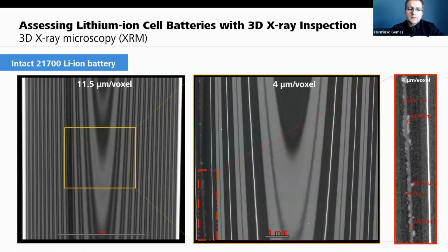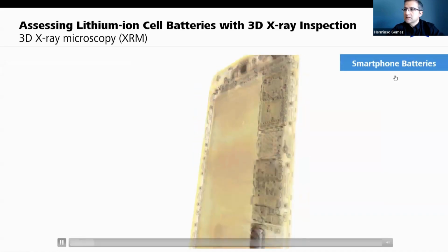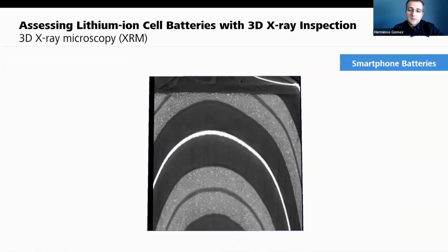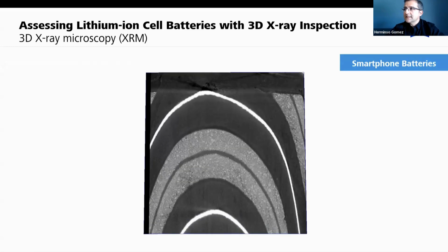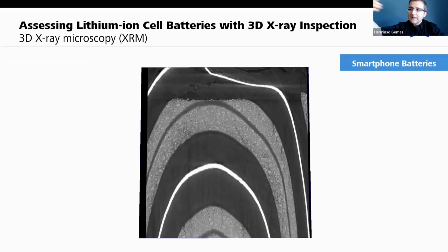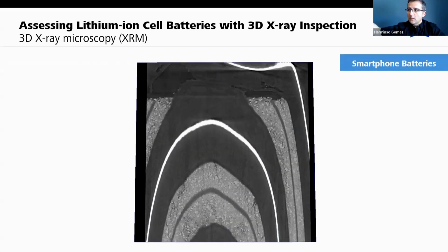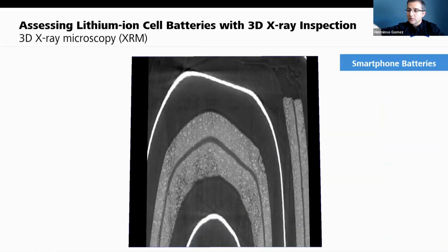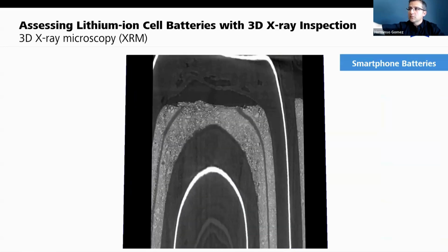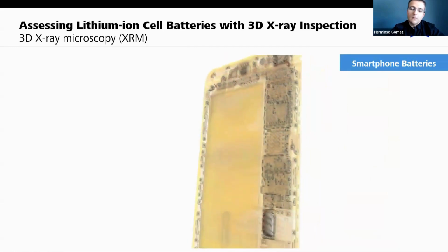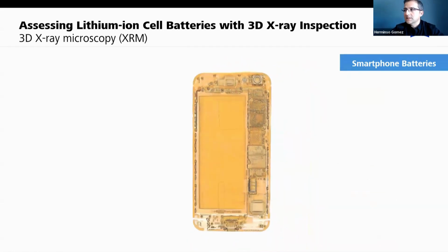And the beauty of this type of technology is that not only do you see high density materials, but you can also see low density materials, as you see there. This is an example of seeing inside of a battery that goes into an electronic component, in this case a cell phone, and you can see over the different layers of the battery, or a section of the battery, without having to cut or crack it open. Just with X-rays, after you do the reconstruction, you can see what is happening in terms of delamination or aging studies of the battery after several cycles of charging and discharging.